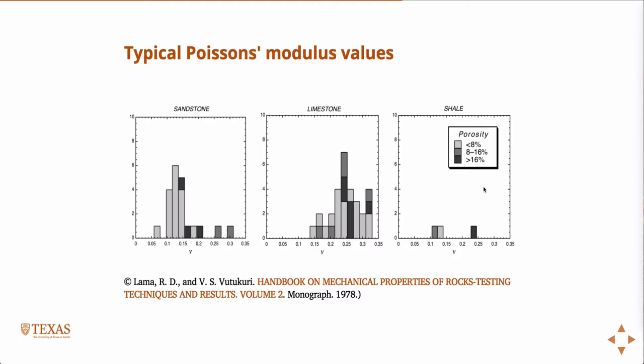But these are some real numbers, and it's difficult. When I worked at Sandia, I used to go down and do some testing at White Sands Missile Range. We would core the granite where we were going to do some testing. You guys have done unconfined compressive strength tests in your lab — we would core the granite and do those tests on it. If you take a core from one spot, it'd have an unconfined compressive strength of like 4,000 PSI, and then you could take 6 steps and take one from there and it'd have 14,000 PSI. So it's difficult to do predictions.